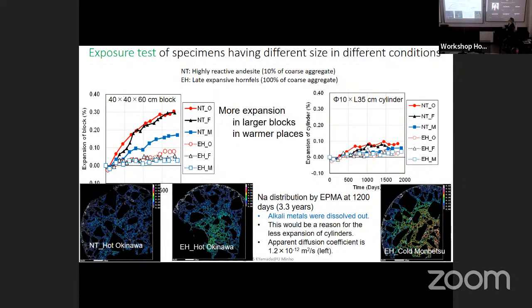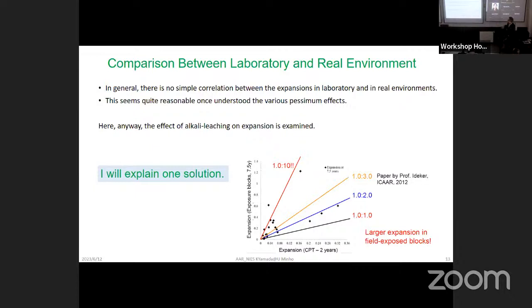We measured the distribution of sodium, and lighter color means higher concentration. As you can see, a significant amount of sodium was lost during 3 years. Of course, without alkali metals, in this case, alkali hydroxide concentration decreases. Then alkali silica reaction stopped. And this is very reasonable. We don't see any expansion in small size. So this may be some reason.